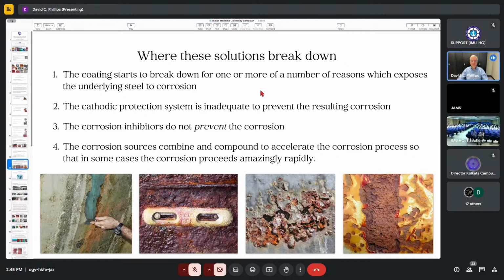However, there's a point of breakdown which is common to all corrosion, which is the coating. If your coating starts to break down for one or more of a number of reasons, the underlying steel is exposed, and then you start the long slide. Why would a coating break down? Well, it could be the wrong coating, just an inefficient coating. It just doesn't do its job properly, even though it's put on. You try some cheap coating just to cover it and say you've done it, and you haven't really coated the hull properly. It can be poor preparation, and it very often is, because if you don't prepare the underlying steel thoroughly and properly, it doesn't matter how good the coating is, it's not going to last. It's going to come off. You're going to get delamination, the paint is going to come loose, moisture is going to go through and spread, and you're going to lose your protection.